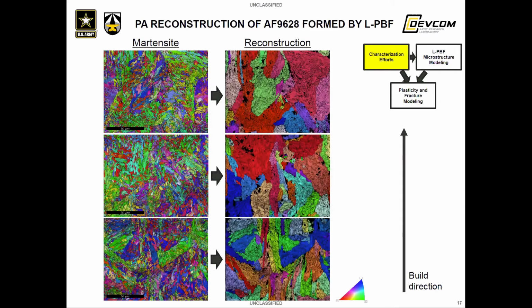Okay. So this slide depicts the reconstructions performed for a few other samples of AF9628. All of them formed via laser powder bed fusion. These were processed using slightly different build parameters, so differing in terms of laser power and scan speed. A more statistically significant data set would need to be gathered, of course, to compare these samples to processing. But even here, you can see a small difference in the austenite grain size between them.